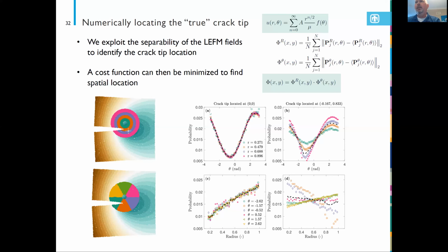And I think that's a really good question. A lot of times when I start thinking about the error in, say, the fracture toughness, I'm relatively surprised that we have such a small error when, say, the shear modulus is off by nearly 10%, right? So to have an interatomic potential that performs as it does, but still gives rise to continuum scale measures that we've gone through this whole rigmarole in order to quantify, I think is a plus for the approach. But you're absolutely right.